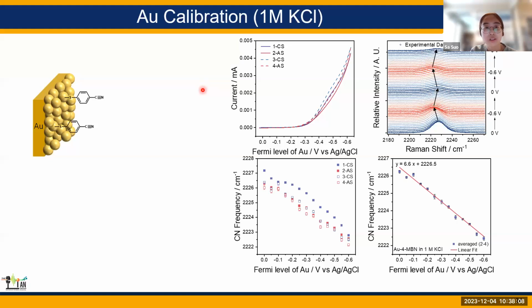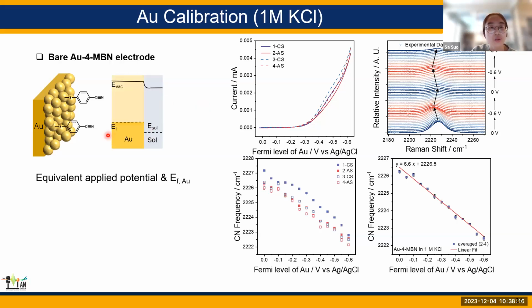Then the logic of using this method to measure the gold Fermi level is as follows. For this kind of metal electrode, the Fermi level of gold is readily known because we know how much potential we apply to this system. If we can measure the nitrile frequency as a function of the Fermi level of gold, then we get a calibration correlation, where if we know the frequency of nitrile in a similar environment in the solution, then we can calculate the Fermi level of gold. This method is based on the Stark effect concept that I gave a talk about a year ago.